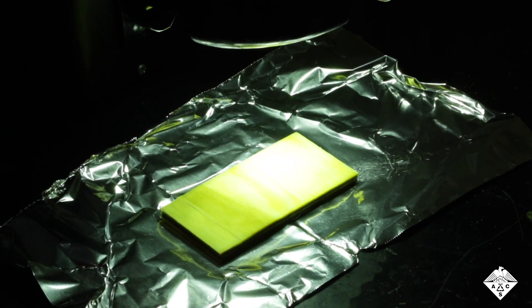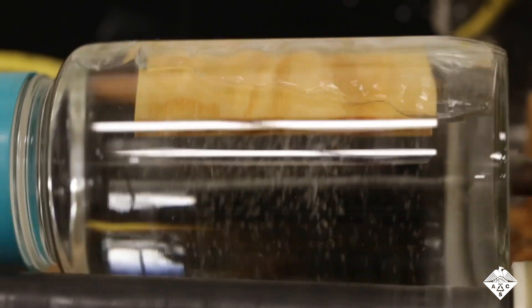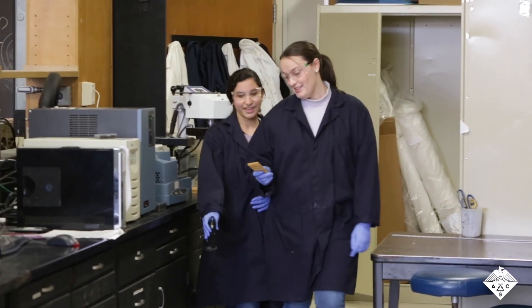That caused the TEMPO to turn the HMP into a negatively charged polymer, which then formed a polyelectrolyte complex with the PEI. The transparent coating is only a few micrometers thick, and it only slightly increased the wood's weight.